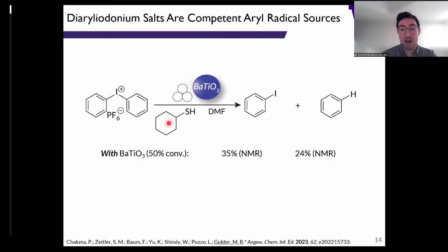We can mill this for about an hour, and we see 50% conversion of our iodonium salt with appreciable formation of both iodobenzene and benzene by NMR spectroscopy. And if we mill in the absence of barium titanate, we see virtually no conversion, and subsequently virtually no production of those small molecule products.